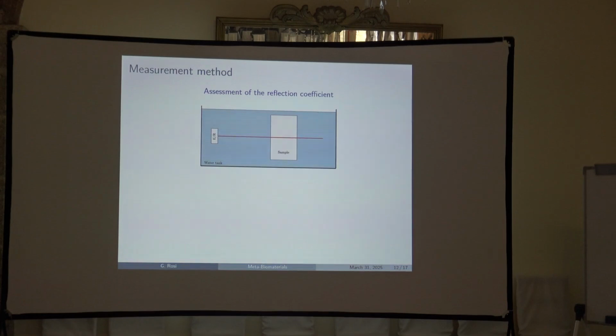So, experiments. Once we validated the simulation part, which was not easy because we had to do experiments to calibrate the properties of the printed materials, we performed the experiment in a water tank. There is a probe here, which is the emitter and the receiver. We send a signal that propagates through the sample, reflects at the surface, and then we measure the reflection. We don't care about the transmission. We measured it, but we didn't use it.